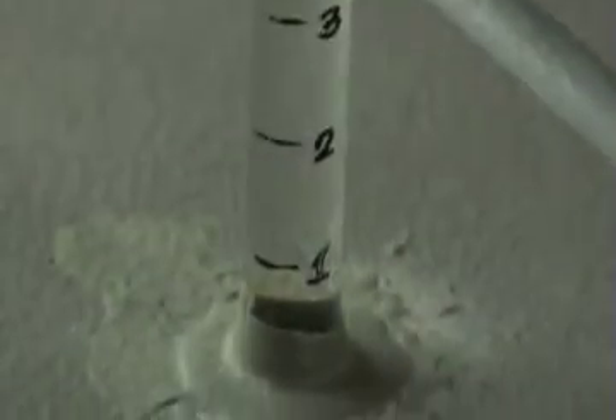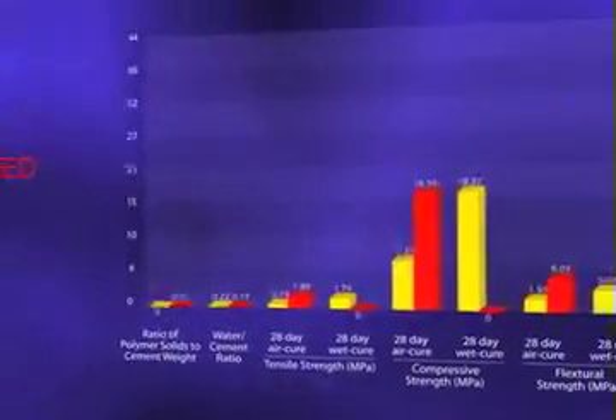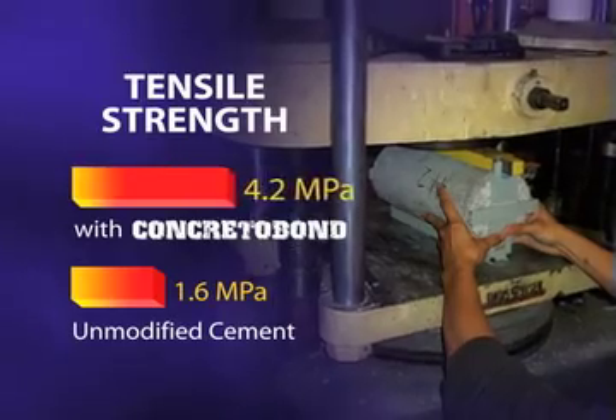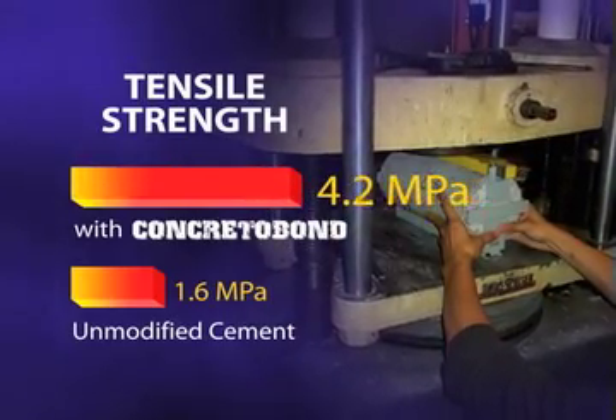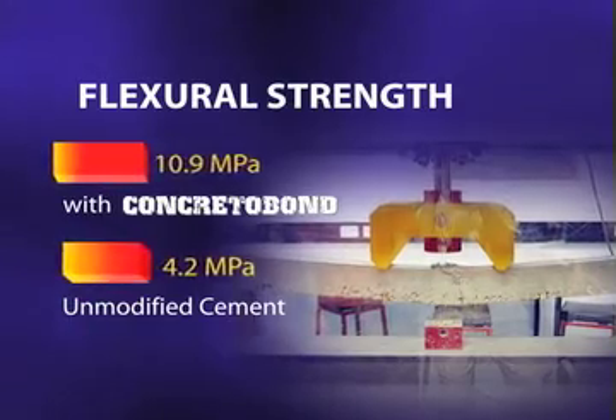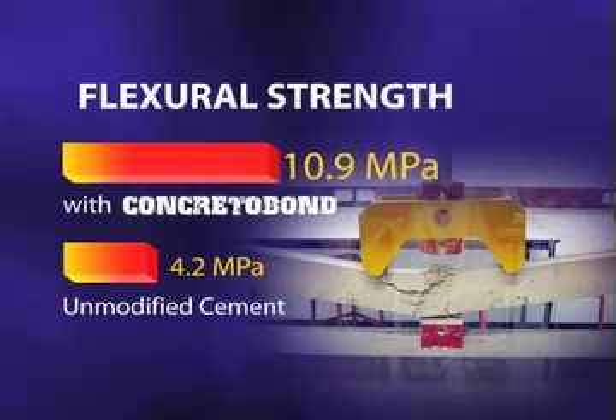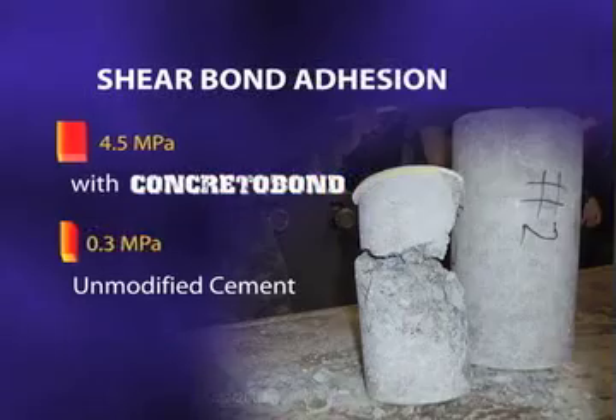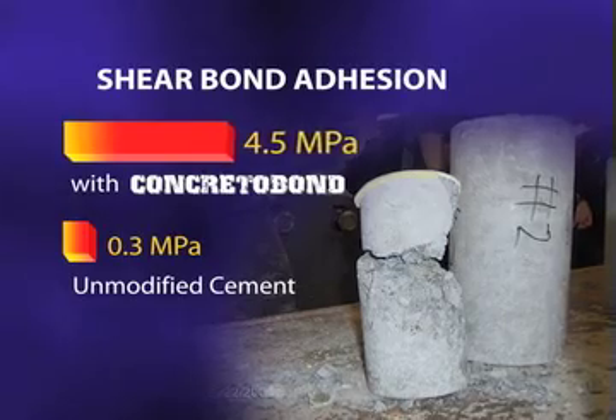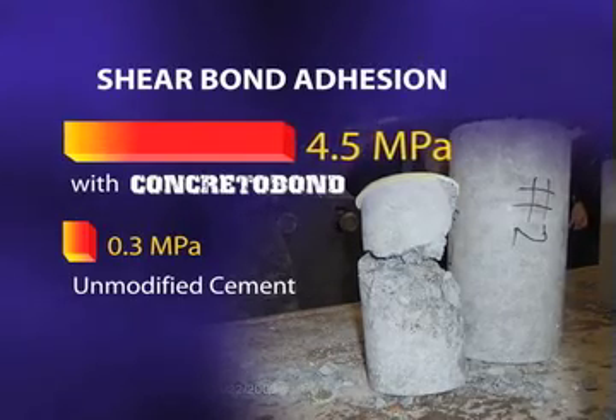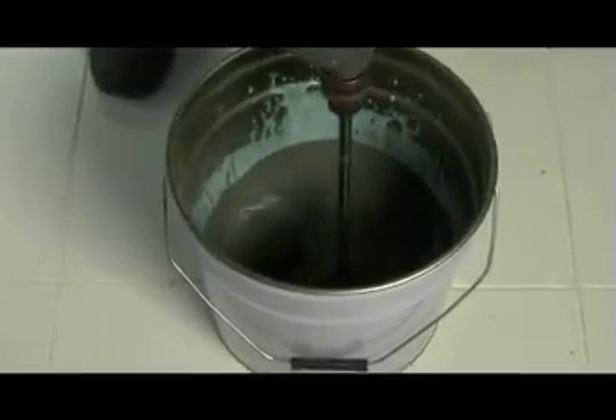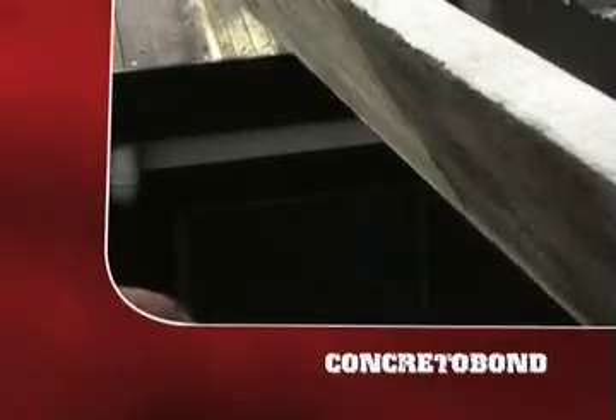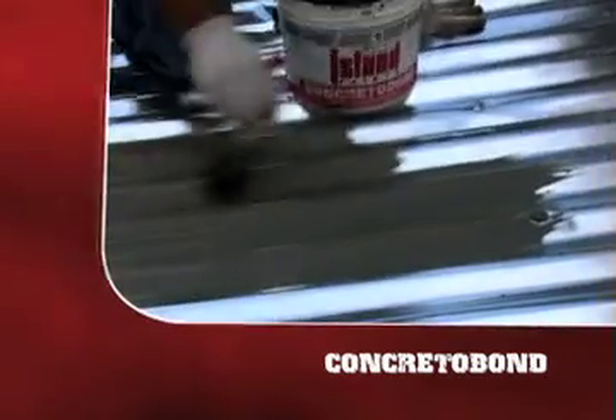Lab tests show that Concretobond improves water repellency. When Concretobond is added to a concrete mixture, it enhances tensile strength by almost 3 times compared to unmodified concrete. Concretobond improves flexural strength by almost 3 times. Concretobond also improves shear bonding adhesion by 15 times, so Concretobond can easily be applied on surfaces that are difficult to adhere to, like old concrete, PVCs, and metal.